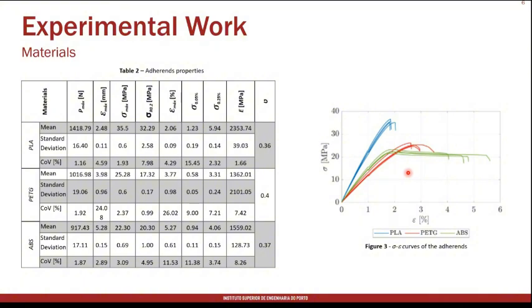I already saw this graphic before today. So here the main issue to retain is that the PLA is stronger but also stiffer than both the PETG and the ABS. So we expect some differences in the failure mode, for example, and in the type of failure of the joint. And in terms of adhesives, we are using a stronger but less ductile epoxy adhesive, which is the Araldite 2015, and a more ductile but less strong SikaForce 7752.